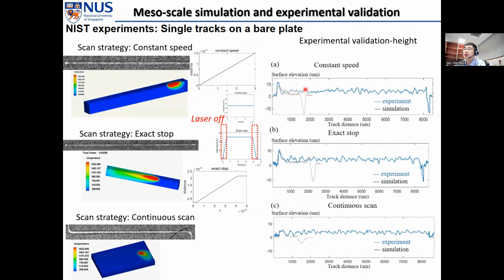So the blue lines are the experimental results. So it's the surface elevation along the track. And the black lines are the simulation results. And you can see the surface elevation is around 10 micrometers in the beginning at the peak, and around 10 to 15 micrometers in the end. So these are due to the Marangoni effect. And our simulation can well reproduce the peak and valley, and quantitatively, the absolute error between simulation and experiments is within 2 micrometers, because our simulation mesh is about 4 micrometers.